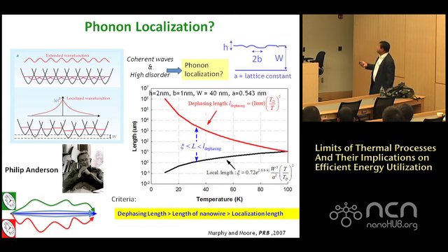So we said let's at least figure out, as a function of the roughness of these wires, the size, and in this case the autocorrelation length, what is the dephasing length and what is the localization length? And it turns out, we were hoping it would go to room temperature. But right now, at least the theory predicts that it's most likely going to happen at lower temperature. And no one yet, to my knowledge, or to the knowledge of all the physicists that have worked on it in the 60s and 70s, has ever shown localization phenomena, Anderson localization, for phonons. If you could localize, then you can really reduce the phonon conductance by interference effects, which is totally wave spectral, which can reduce the thermal conductivity even below the amorphous limit. And that's what we're going after.